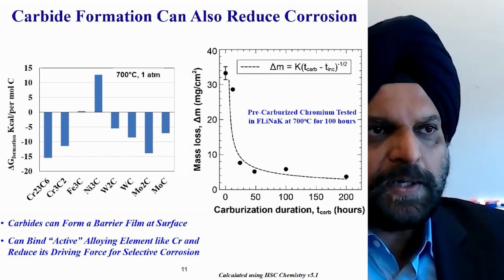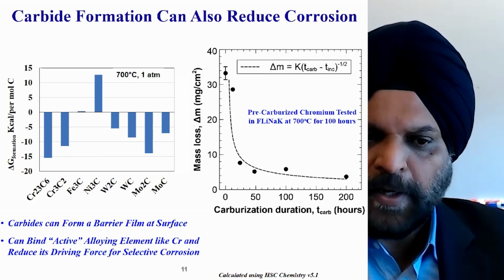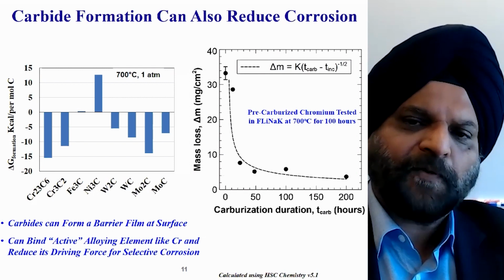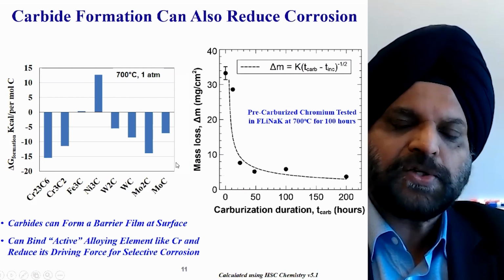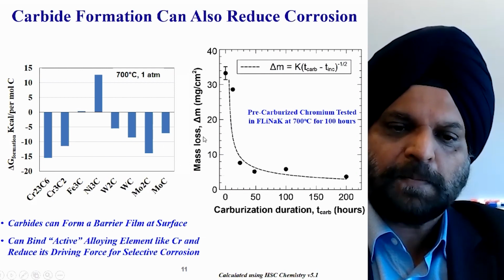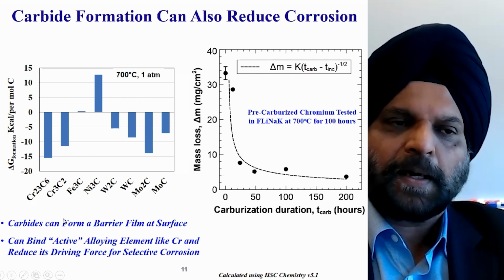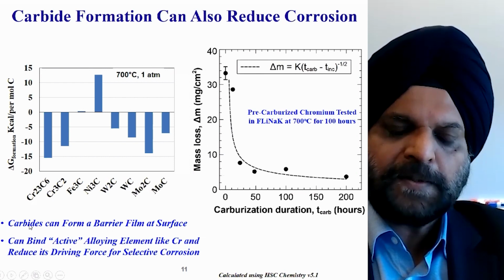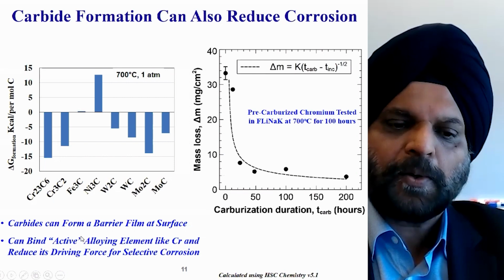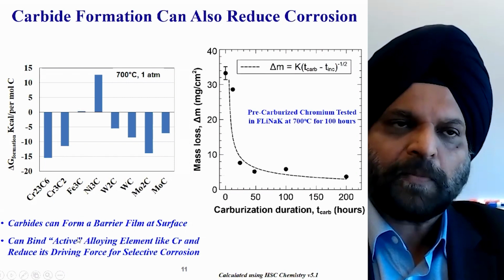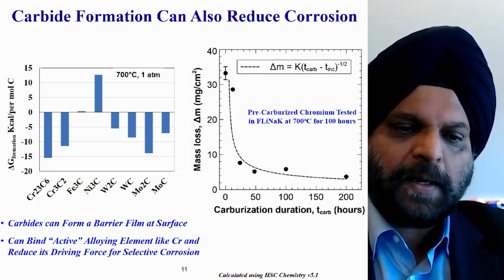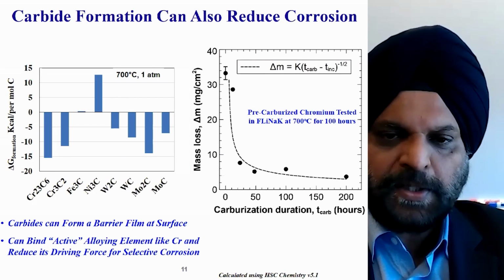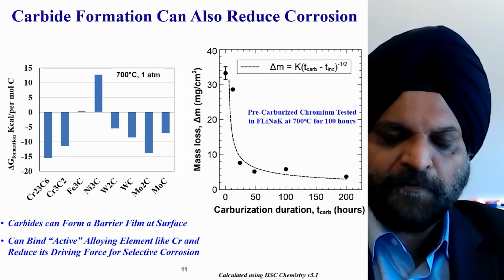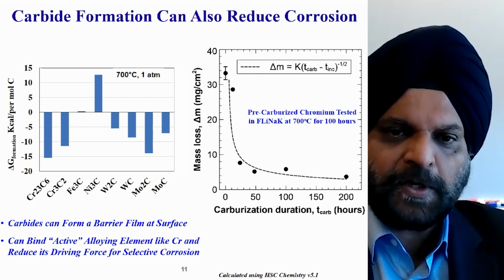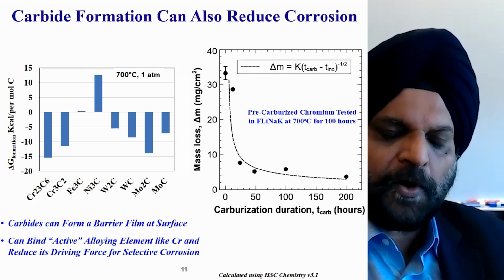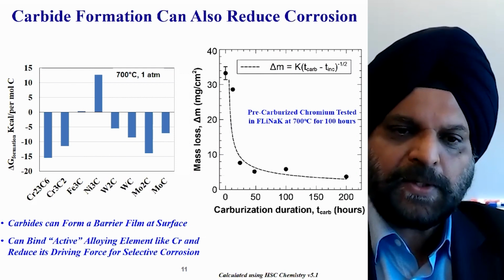So we did a lot of other work on alloys as well, and what we find is that yes, corrosion rate eventually can decrease if you bind a lot of chromium with this carbon at the surface. So chromium carbide lowers the activity of chromium. That is one factor which can decrease corrosion rate, because now the driving force is lower: the activity of chromium available for reaction with fluoride has gone down.